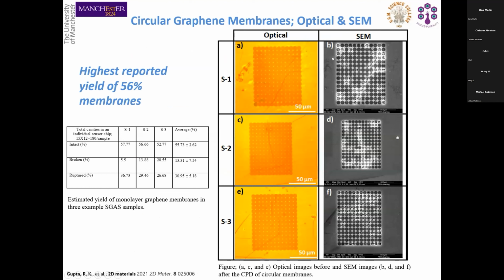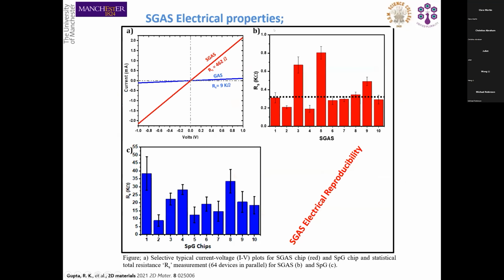As I said, it's very difficult to have 100% yield because this all depends on the graphene properties. But with the methodology that we used, and which we protected as know-how and as a patent, we could get up to 56%. The idea is to get 100% yield, but that only comes with high quality graphene.